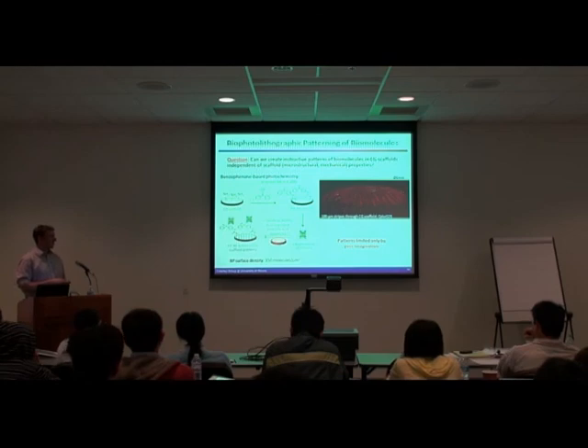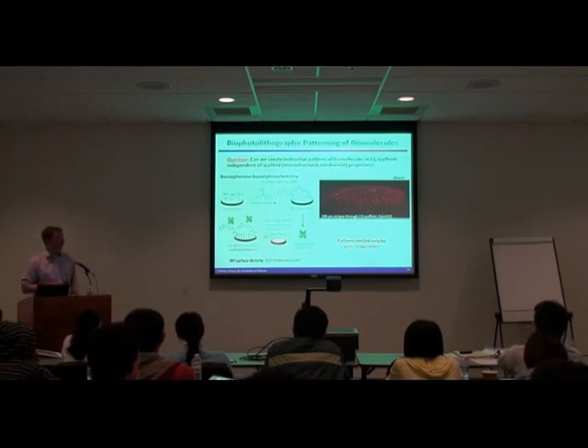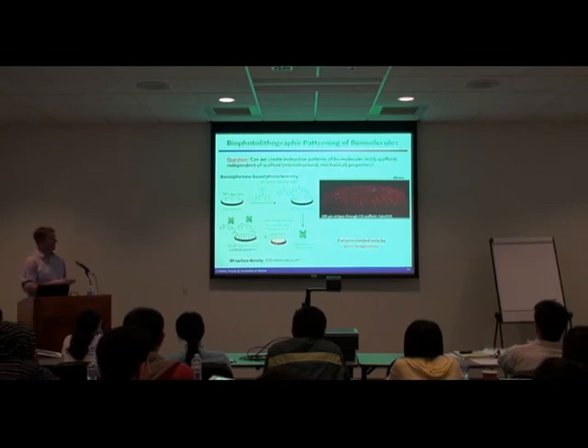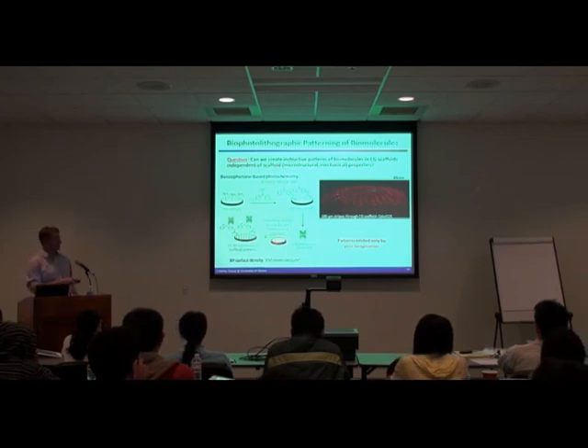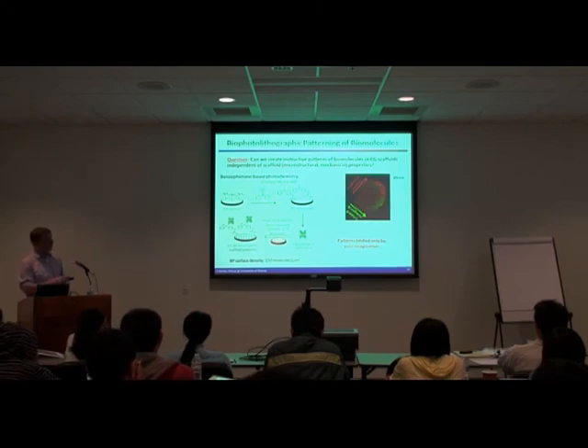So we're just starting to mess with this, but we're doing about 350 molecules per micron squared, so it gives us the ability to pattern locally at the resolution of UV light, or starting out to use some two-photon microscopy approaches to pattern structures into our scaffold. So this is a uniform isotropic scaffold that we've now patterned stripes of, in this case just a quantum dot for imaging purposes, all the way through the scaffold. Or it can do bidirectional gradients of N-cadherin to look at cell-mediated attachment.